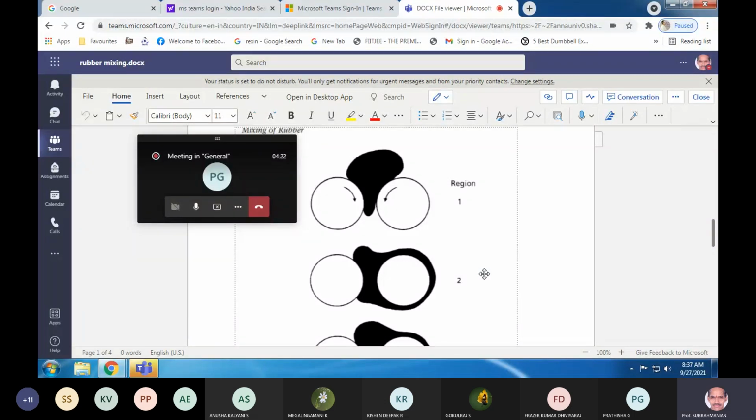Friction ratio is just about 1:1.15 in many cases. In select cases, it increases to 1.2. A higher friction ratio is required to handle the components that are difficult to disperse. We will come to all that.